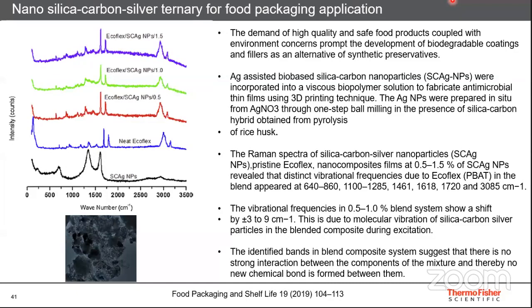In this study they wanted the food packaging to have antimicrobial activity. That is why they made a silver bio-based material from rice husk. They prepared these silver nanoparticles using a ball milling technique, and these materials were then incorporated into a viscous biopolymer to fabricate this antimicrobial thin film. They wanted to study how that material has been formed and how the silver nanoparticles interact with the material. All this study they could do using Raman spectroscopy.